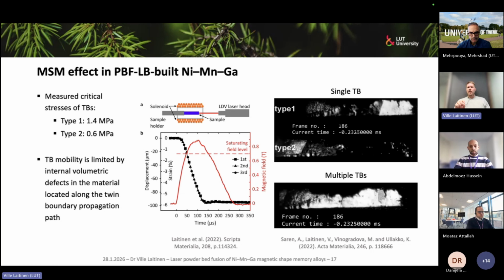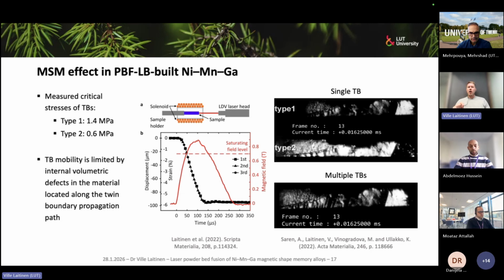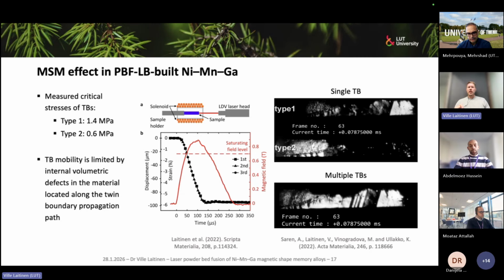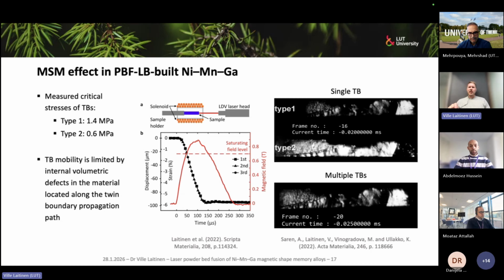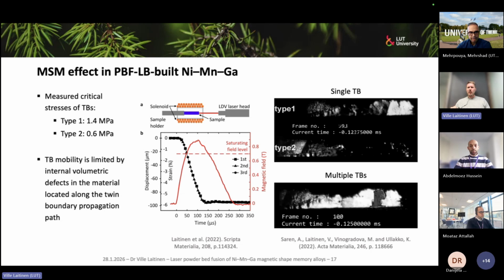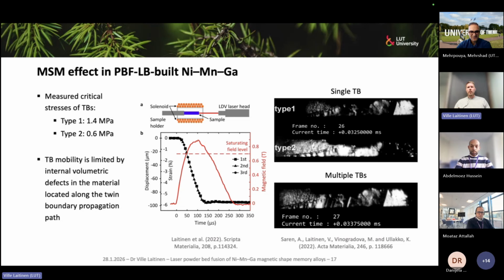So the type 2 twin mobility is so high that it's almost impossible to take a good electron microscope image of it, because in the electron microscope we have an electron gun, and the electron gun generates a magnetic field. The magnetic field generated by this gun is so high that it can actually move this type 2 boundary out of the sample. So it's a very highly mobile boundary.